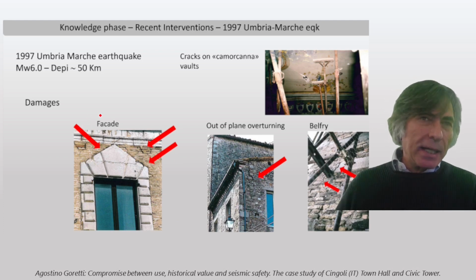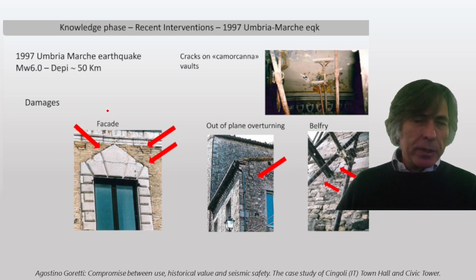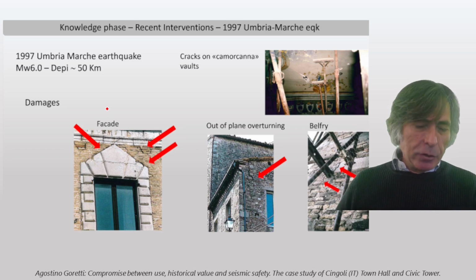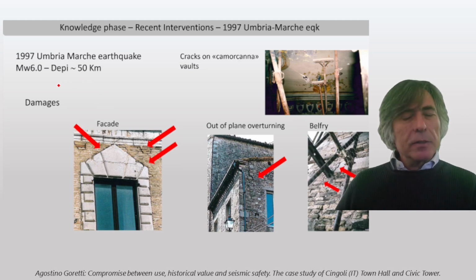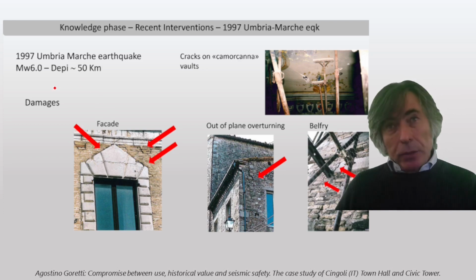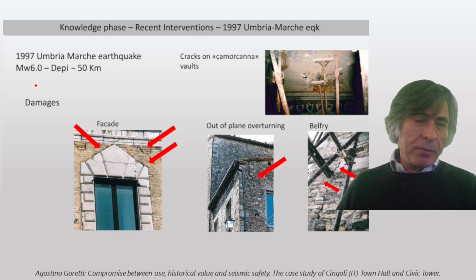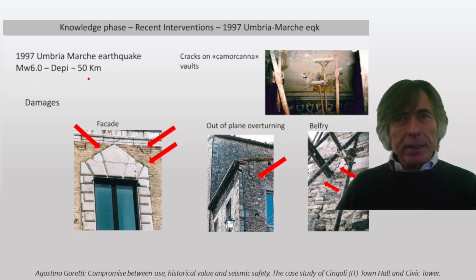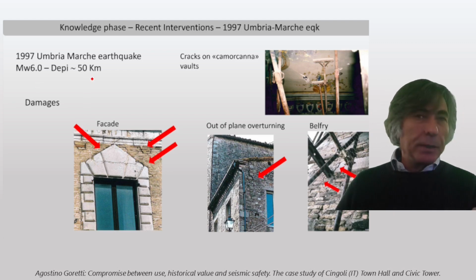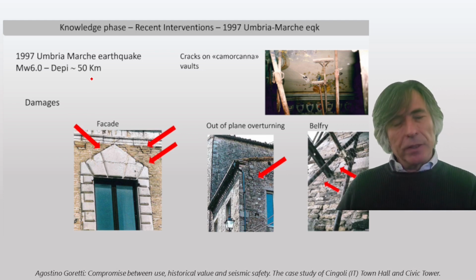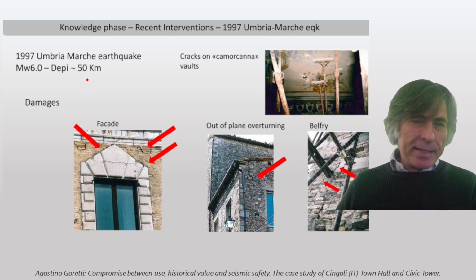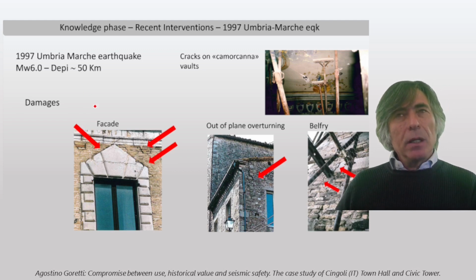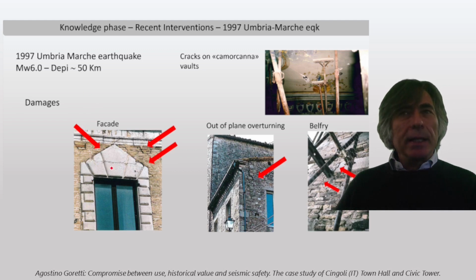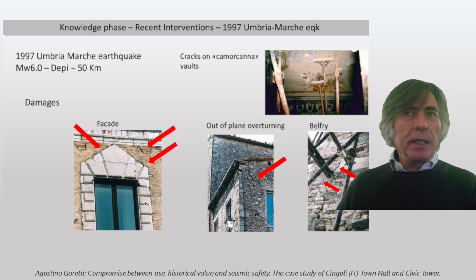And we arrived at the 1997 Umbria Marche earthquake, which was the earthquake that Cingoli municipality suffered before the 2016 earthquake. It was at that time an earthquake with a lower magnitude, 6 instead of 6.5, and the distance from the epicenter was 50 kilometers, so a little bit less than the 60 kilometers of the 2016 earthquake, nevertheless not in the epicentral area. At that time the damages were mainly in the separation of the heavy decoration of the facade from the brick wall of the